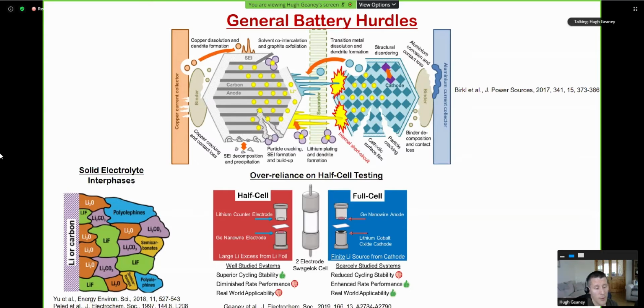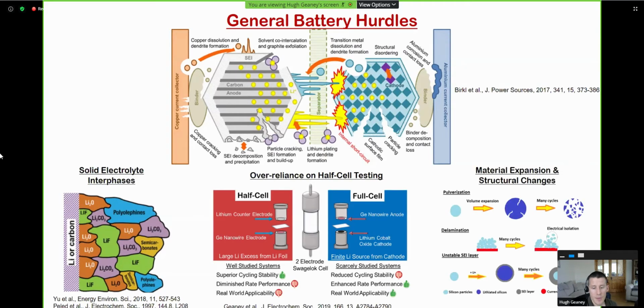Essentially, it doesn't properly mimic what's going on in a full cell. Again, this is our full cell, this is our lithiated metal oxide, and this is our active material here. We could do a huge amount of development of an active material, and if we've only ever tested them within half cells, we could completely neglect really important issues that are going to crop up as we develop these further on.